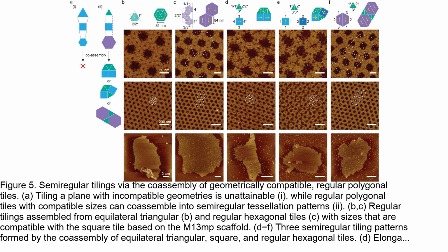The study demonstrated the general applicability of the design method by creating 9 different tile geometries, 15 unique tile designs, and 12 tessellation patterns covering Platonic, Laves, and Archimedean tilings. The optimized tessellation system produced single crystalline lattices ranging in size from tens to hundreds of square micrometers. The authors also explored strategies to increase the complexity of DNA origami tessellation, including reducing the symmetry of monomer tiles and co-assembling tiles of different geometries. The study opens up new opportunities for applications in metamaterial engineering, nanoelectronics, and nanolithography.